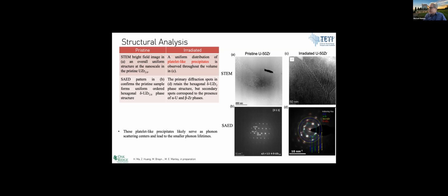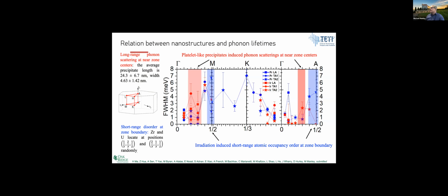But yeah, X-rays allow us to see these things. These are the actual size of the platelets, 24 nanometers by about 4.6. And so the middle of the zone corresponds to wavelengths that are around those length scales. So that part kind of makes sense.